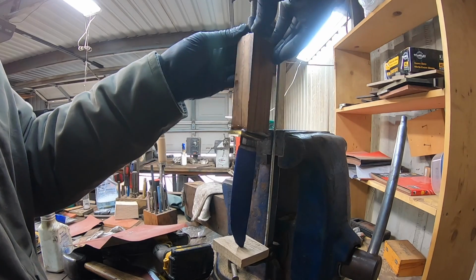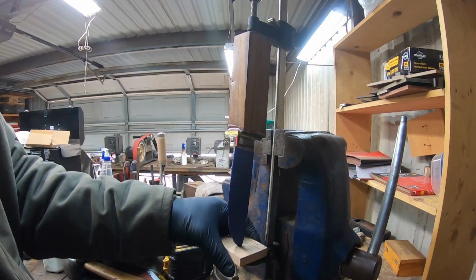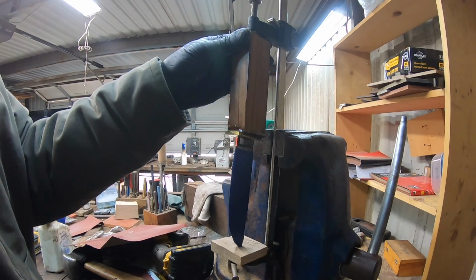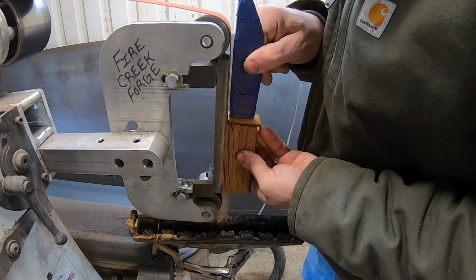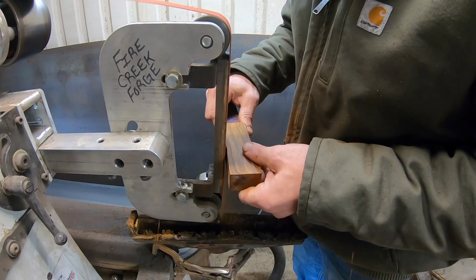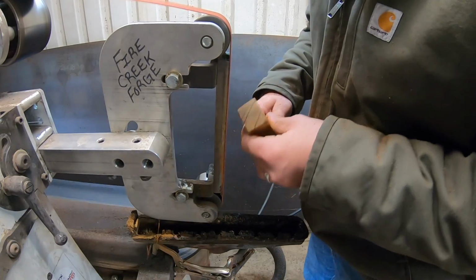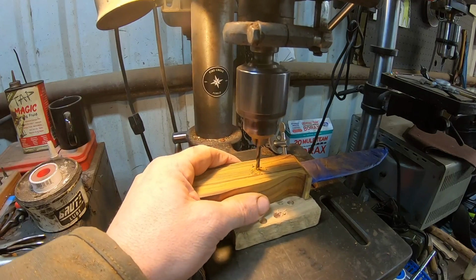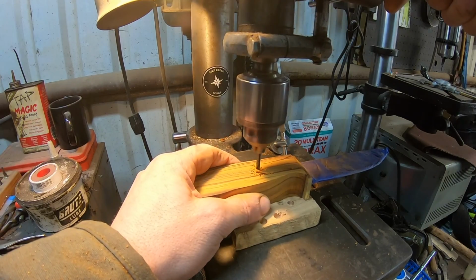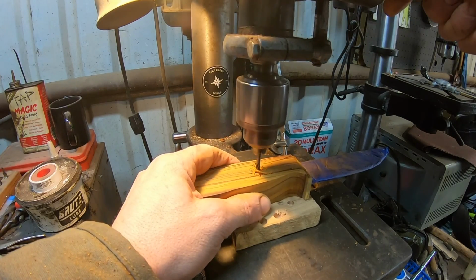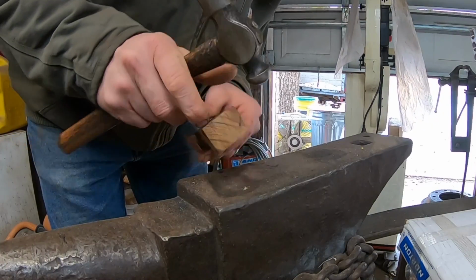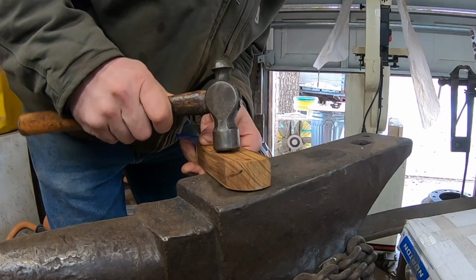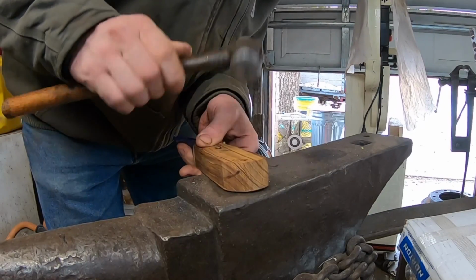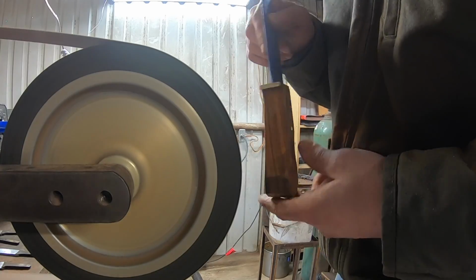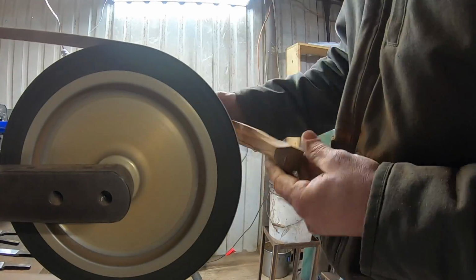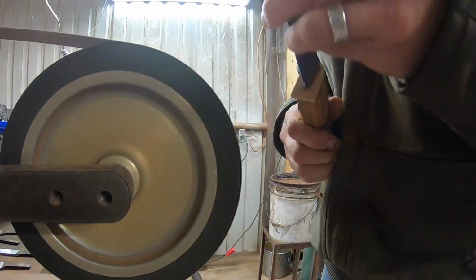Put it in the clamp, let it set for a while, and then I can install the pin through the tang, which reaches almost the full length of the handle, and that'll provide a super strong mechanical bond or lock for this knife construction. This is a 5/32 pin set in with epoxy and peened over with the hammer, and that'll keep everything nice and tight. We can grind that off flush and everything is going to stay where it's supposed to be.